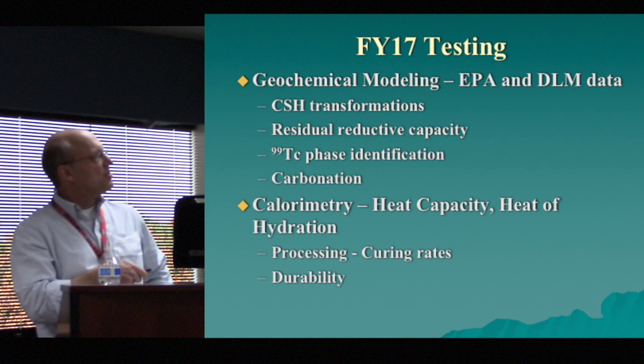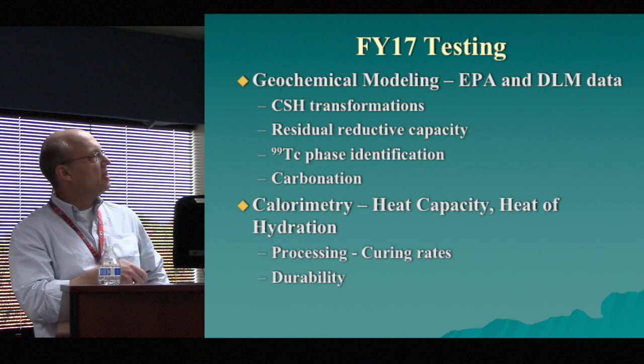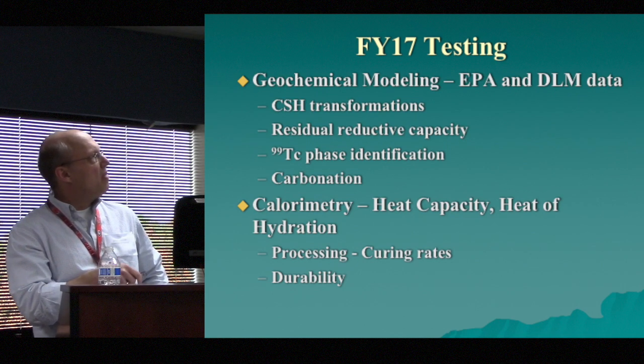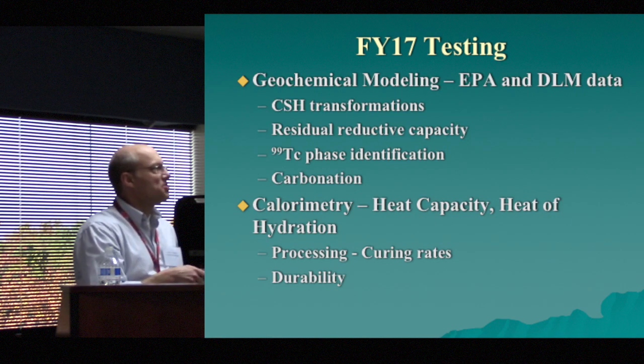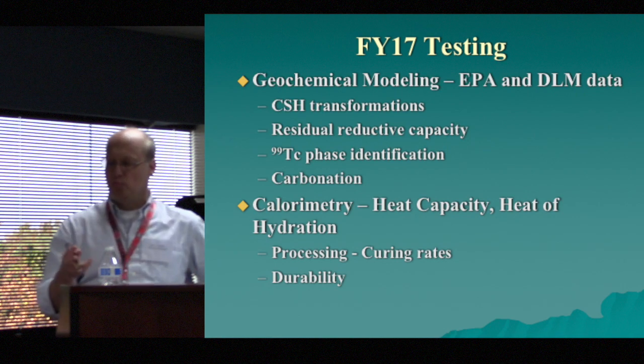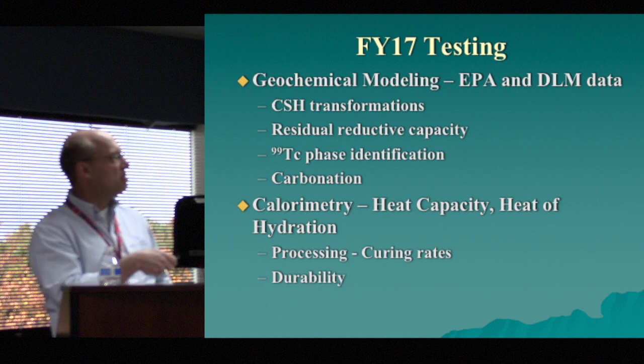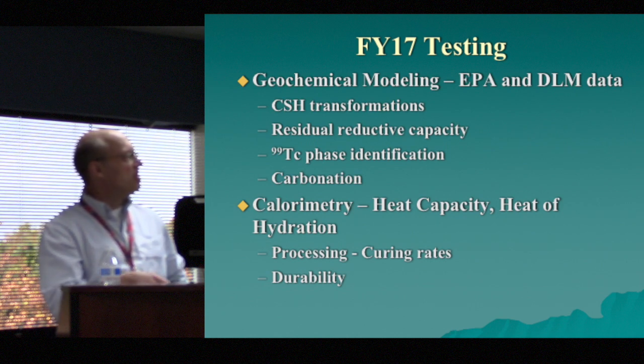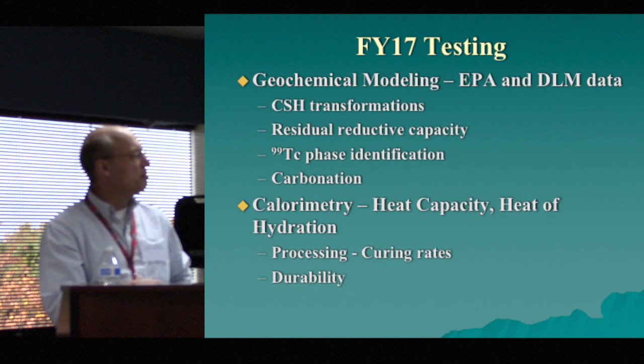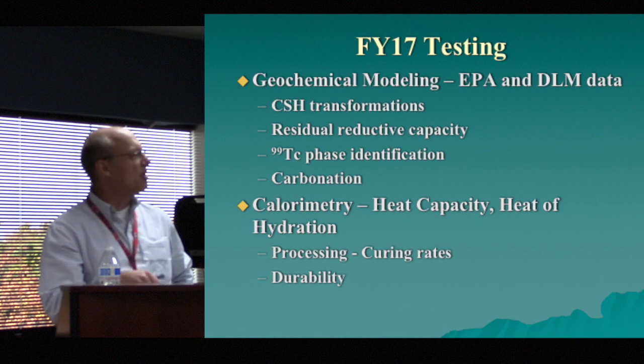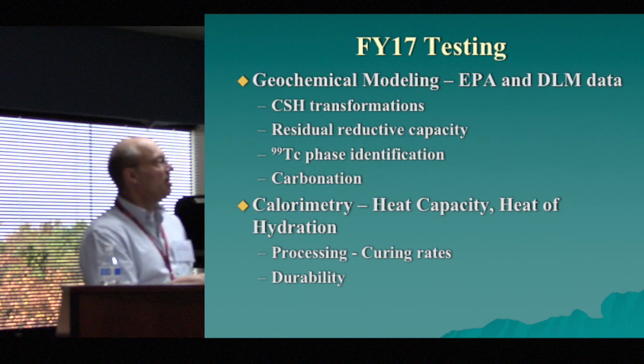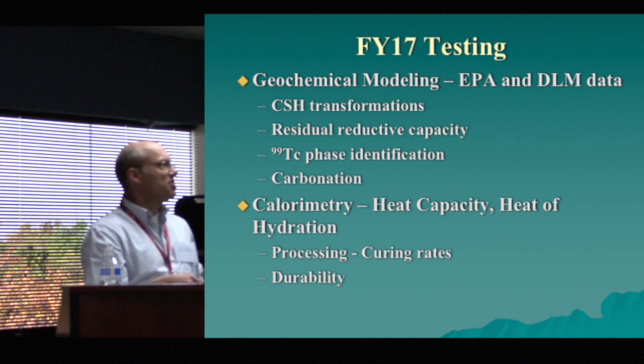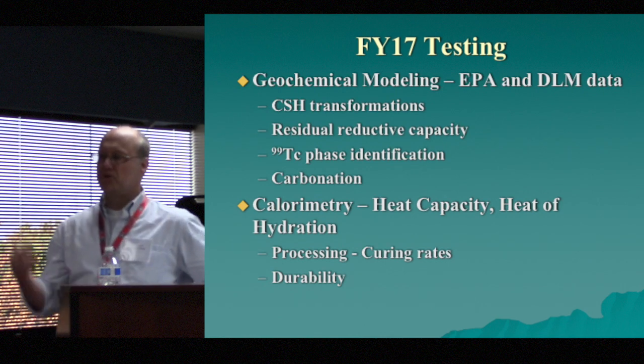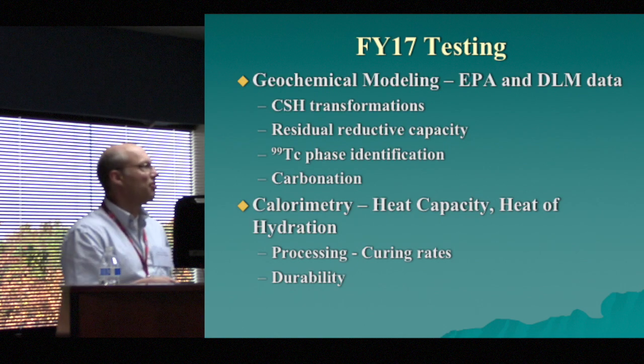Geochemical modeling. We've started doing some modeling of this, looking at the calcium silicate hydrates that are generated in cementitious material and trying to see what the major phases are that are controlling the chemistry of the material. We're also looking at what the residual reductive capacity of the material is. We're trying to identify, using some of these, more specifically what the Tc-99 may be controlled by. And then we're looking at changes in the material over time, something like carbonation and things that change the properties of the cement over time, or the grout.